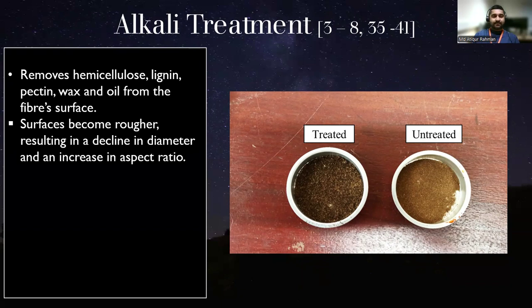So we did the alkali treatment. That is very common, and that is economic as well. There are other treatments as well, silane, then permanganate, but we use this one because it is very cheap. The main purpose is that after the treatment, the surface becomes rougher, resulting in a decline in diameter and an increase in aspect ratio, and that helps enhance its mechanical and thermal properties.